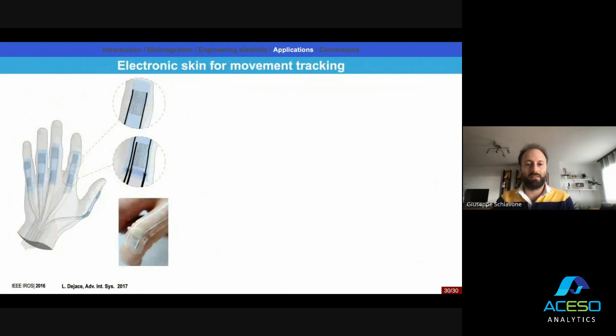Here you go. We made devices that were very similar to the membrane with the LEDs that I showed before. The layout of the device looks like what you see there on the left. You see the hand, and you have devices with serpentines laid on the joints of the hand. These serpentines act like strain gauges. If you stretch this device, the resistance of these conductors will change, and you can detect that. If you apply this to the joints of the hand, when you move the hand, this will automatically stretch the device, and therefore produce a change in the resistance of these conductors.